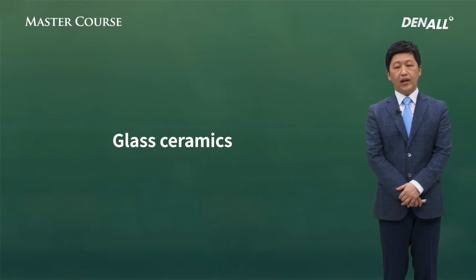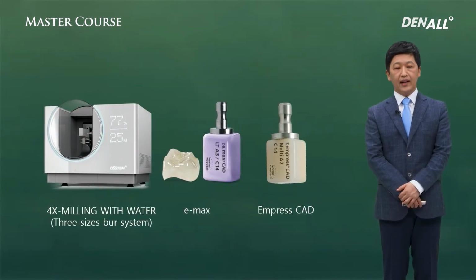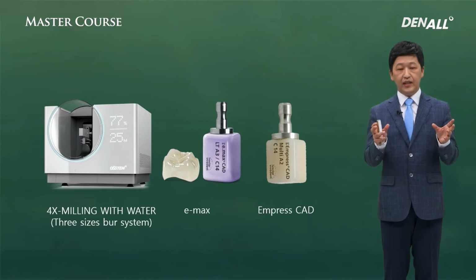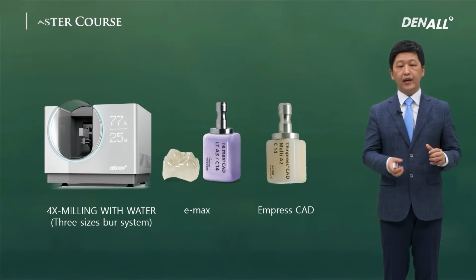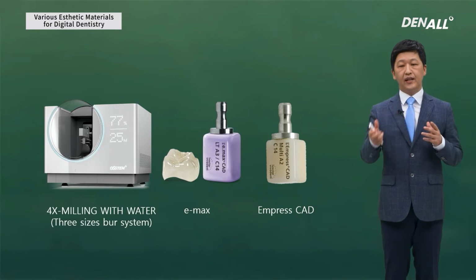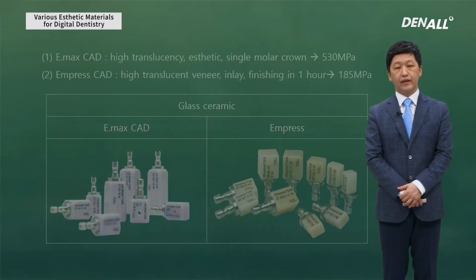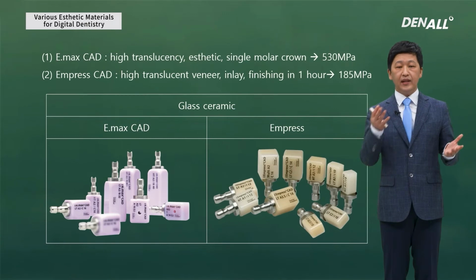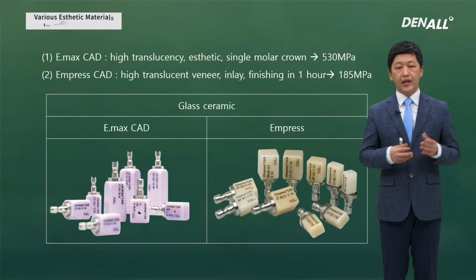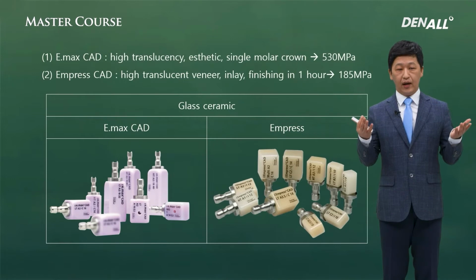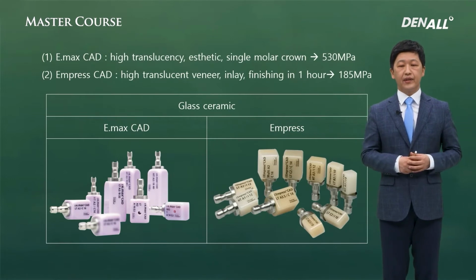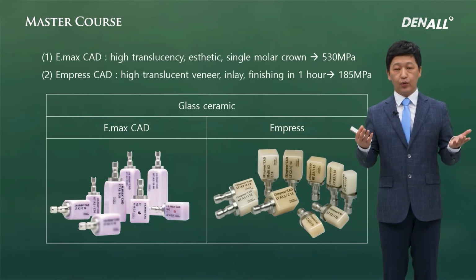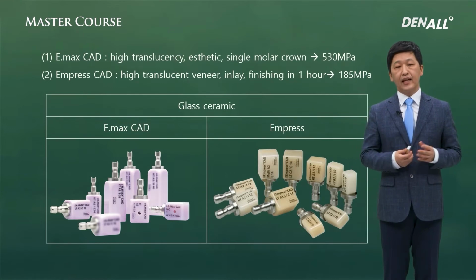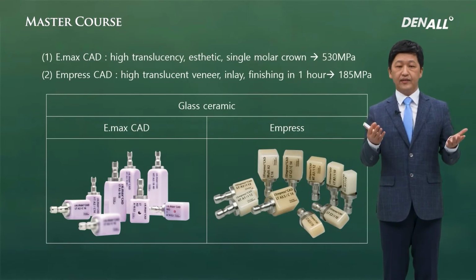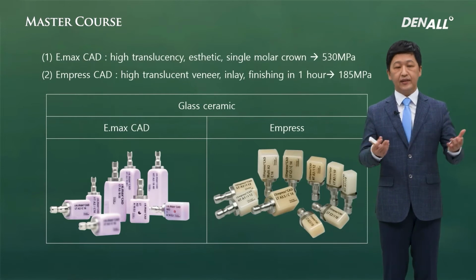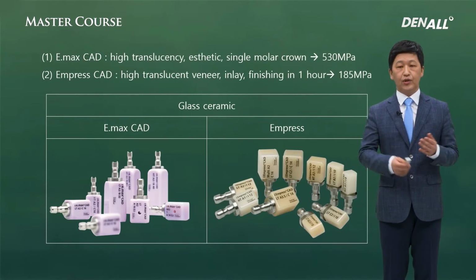The second aesthetic material is glass ceramic. The glass ceramic is in the block form and it is mounted on the 4-axis milling machine to be milled with water. The representative ceramic material is Emax and Empress. Emax has the strength of 530 megapascal and Empress has the strength of 185 megapascal. So if you want some strong material, Emax is recommended rather than Empress.